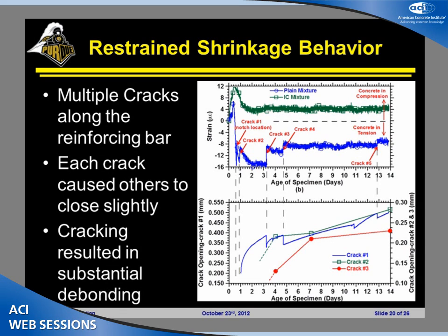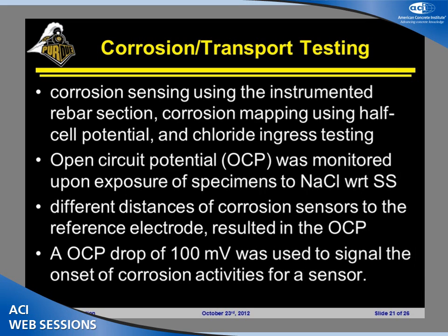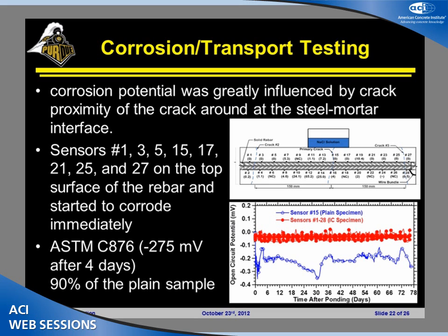The other thing that I want to point out that this really doesn't capture: this gives us a crack width, but it doesn't give us how much of the bar is debonding when that crack starts to form, and how much of an opening is happening in that system. So as mentioned, we're going to be monitoring corrosion in the system. We're going to be using the sensors. We're going to be using half-cell potential, and then we're doing additional chloride testing.